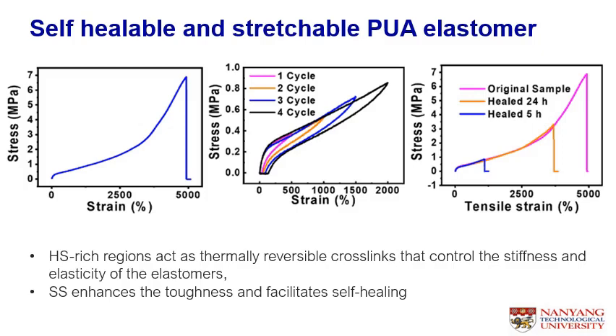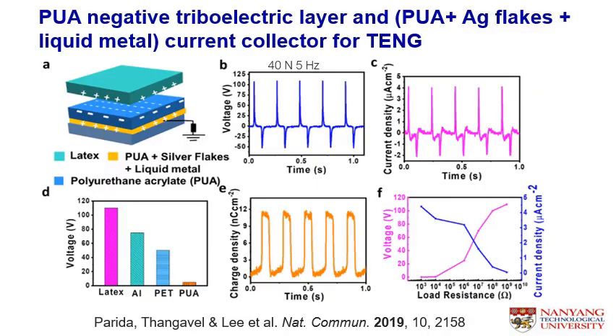As we can see here, upon healing at 24 hours, it can recover the mechanical stress strain up to a certain percentage. This PUA material can be used as a negative triboelectric layer. Using the similar matrix by adding in silver flakes and liquid metal, we use it as a current collector for the triboelectric nanogenerator. As we can see in this performance of 40 Newton at 5 Hz, it can consistently provide an output voltage of 100 volts.